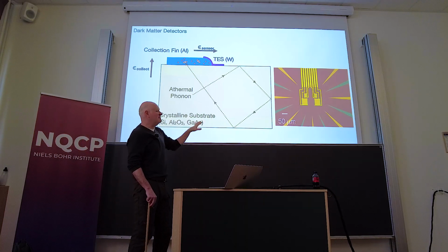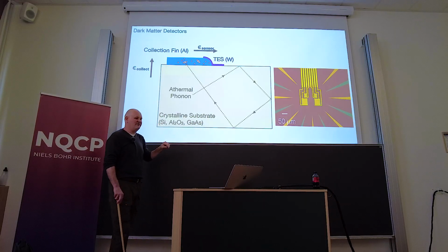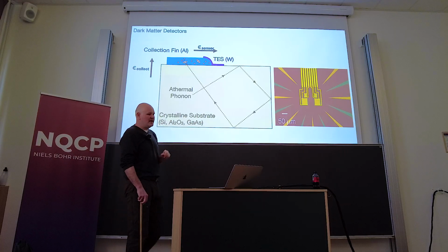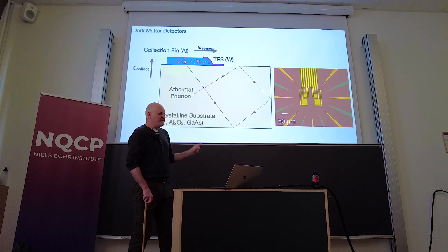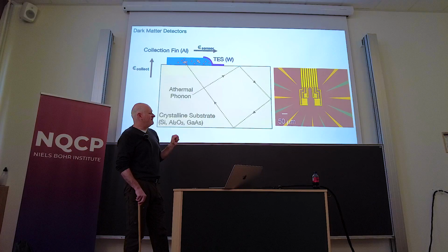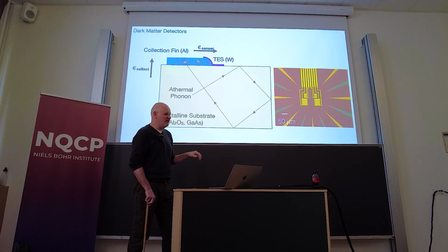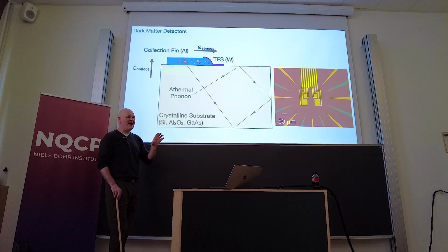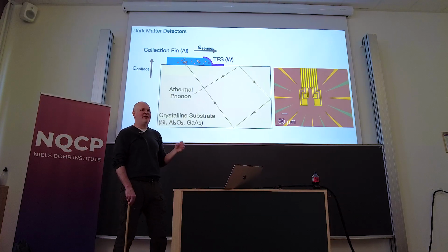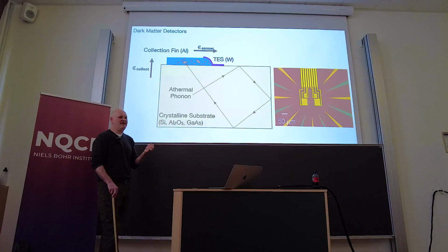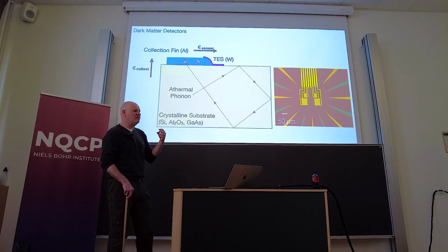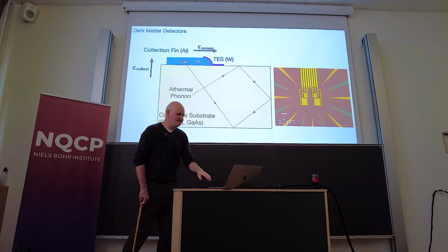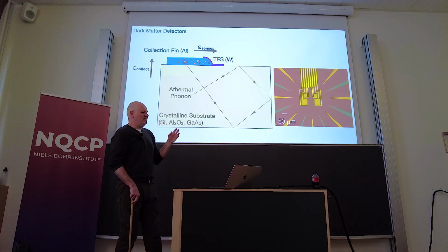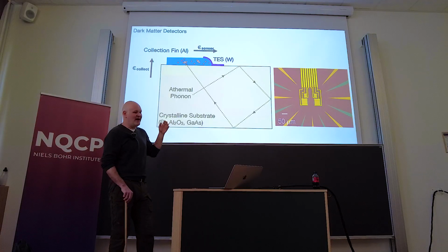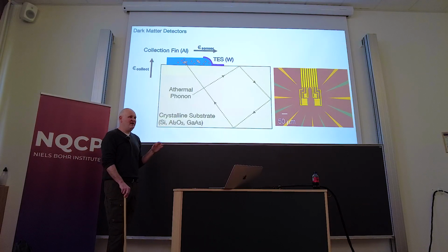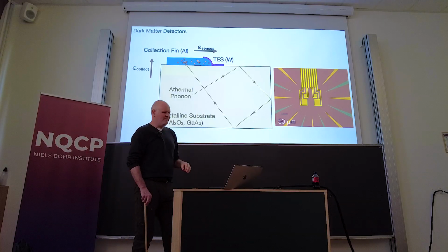And so these can be used for all kinds of things. It's not just this. These are also used for single photon detectors and all kinds of stuff. But the thing that's interesting to me is that unlike for quantum computing or many things, rather than trying to have a higher TC material, you actually want to have lower TC materials. You want materials that are very, very close to losing it, basically the Cooper pair is falling apart. So very low energy Cooper pair bonding. The way that they go about this is they use something like tungsten or hafnium, which has a very low TC in the hundreds of millikelvin, because it's very close to falling apart.